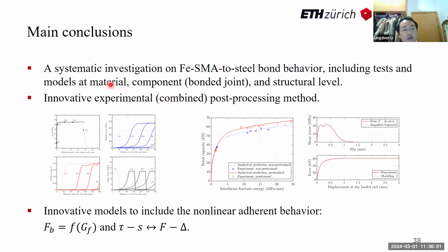In this PhD work, I conducted a systematic investigation on shape memory alloy to steel bond behavior from the material level to the component level, which means bonded joints, to finally the structural level. They include the tests and the models. I used an innovative post-processing technique to analyze the experimental lap shear behavior. I developed innovative analytical models to predict bond capacity and also to analyze the bond slip behavior directly from the